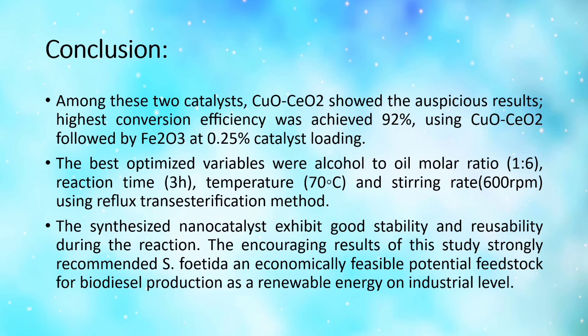So this study concluded that among these two catalysts, the copper oxide and cerium oxide composite showed auspicious results. The highest conversion efficiency was achieved, that was 92% using the copper oxide cerium oxide composite, followed by the iron oxide, at 0.25% catalyst loading. The best optimized variables were alcohol to oil molar ratio 1:6, reaction time 3 hours, temperature 70 degrees Celsius, and stirring rate 600 rpm using the reflux process.